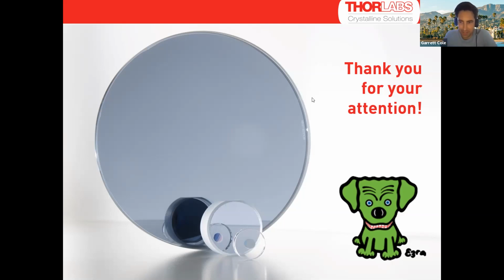So I should have mentioned this earlier and I forgot. We add a flat to maintain the crystal orientation, so we know what the orientation of the stack is. Our materials are birefringent. So if you have an application that you cannot deal with birefringence, you don't want our coatings. This is really interesting because on paper, 100 gallium arsenide, which we use, has 0 birefringence.